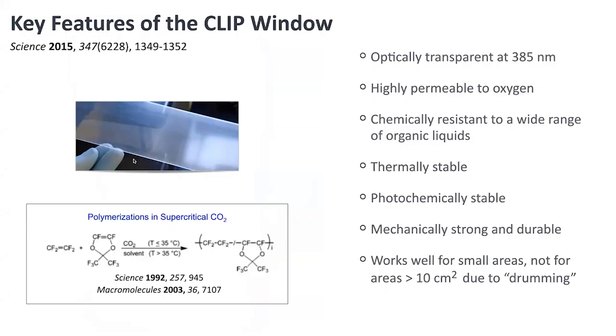And so let's walk through some of these things. The window is back to that fluoropolymer, a Teflon AF type material, optically transparent, very permeable to oxygen, very chemically and photochemically stable. But you've got to think about it, there are a lot of forces, adhesion forces, as you pull the object up and you're sucking liquid into that gap. And so the window can drum, and this works well for small areas, but you've really got to be thinking about the window. A stiff window is really needed in order to have liquid be pulled in and the window not deform, because you'll deform the object. And if the window is a liquid window, there are some reports of that in the literature, liquids are more deformable than films are, and it can get pulled up into the part and can be problematic. So it's not just an adhesion issue, it's a mass transport of the liquid underneath.